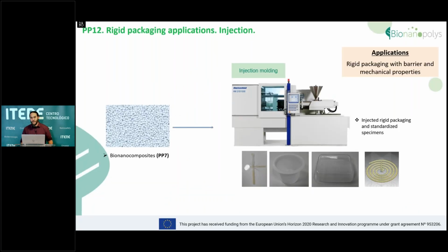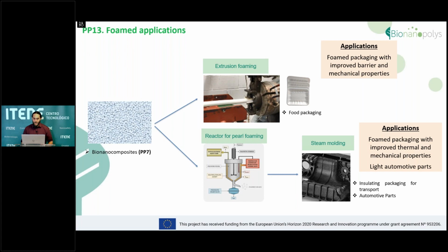And for rigid packaging applications, we have here at ITENE an injection molding machine that allows us to obtain standardized specimens of different natures, like trays and caps and specimens for mechanical properties testing. Our partners from CIDAUT for this pilot plant 13 are bringing the capabilities for foaming applications. They have extrusion foaming equipment to make foaming packaging, food packaging from foamed beads, and also they have a reactor to make the swelling and the expansion of these beads that could then be made into complex parts, for instance, for the automotive industry by steam molding.